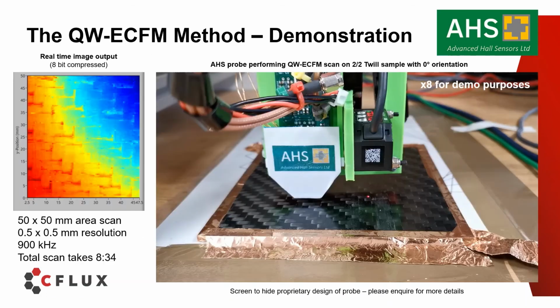The real-time image of the scan is being shown. Firstly, a lift-off map of the sample is compiled using the proximity laser on the same probe. As shown in the image output, there is some slight curvature or tilt to the sample from bottom left to top right. This is used to autonomously control the lift-off of the probe to maintain a consistent 0.5 mm above the sample surface, to not only avoid probe sample damage, but also for better quality images.